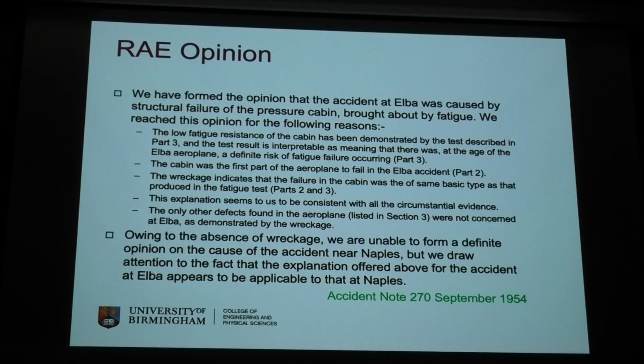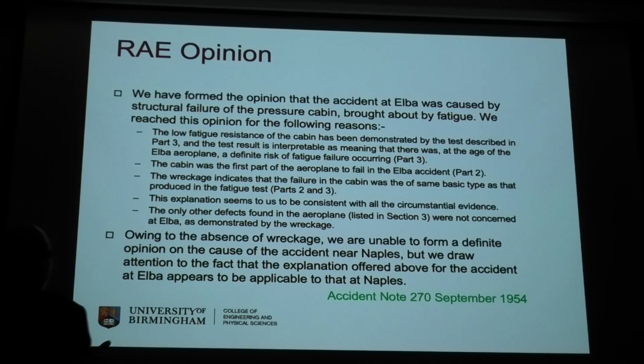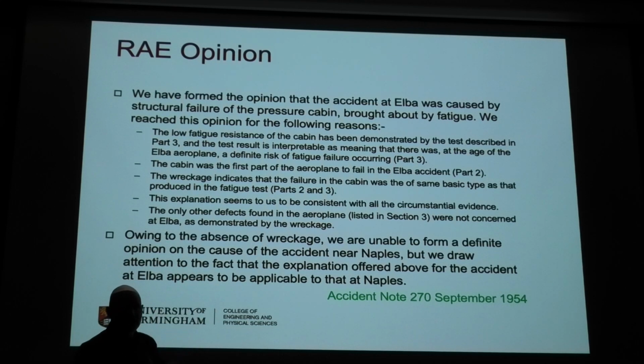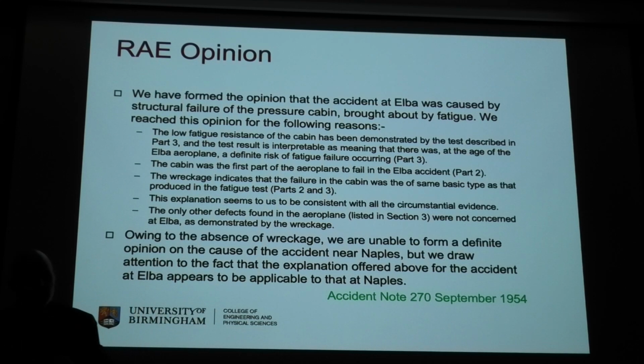And so we end up with the RAE opinion that says we're pretty certain that it's all due to fatigue, and that's just the wording of it in accident note 270, basically saying that it's definitely fatigue, it's come from a bolt or a rivet hole, and it's grown to a critical length, and it's popped the fuselage when it's reached the critical length, and the stress has forced it through. And that because there's no wreckage from Naples, it's probably exactly the same cause due to forensic evidence. Now that was picked up by the Court of Inquiry, that became the standard response, the official line on what caused it.